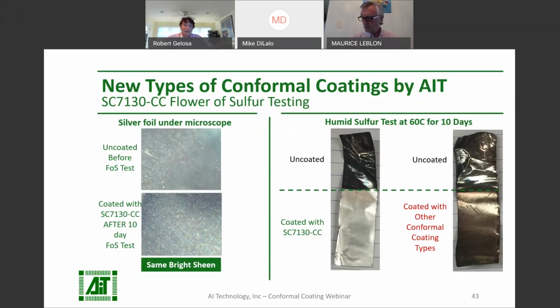On the left-hand side of this slide, we can see a silver foil under microscope. The top image is uncoated. The bottom image is after being coated with AIT's SC7130-CC and then a 10-day flower of sulfur test. The sample keeps its same high gloss and smooth appearance. The flower of sulfur test is used to examine the susceptibility of test articles to sulfur-based corrosion. It was originally developed to test the porosity of metallic coatings. We can see that a sample coated with AIT conformal coating shows no change after 10 days of the humid sulfur test, where other conformal coatings can't provide the same level of protection.